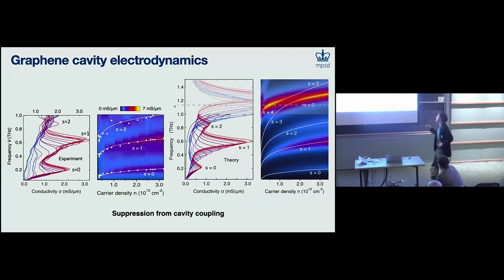So I think there's a few reasons. Clearly, this mode down here, look in the simulation because it's easier. The black line here is the graphene cavity mode. So you can see this mode down here, there's no spectral overlap. There's no spectral weight in the cavity mode, so that's why that mode is not really affected. But as soon as you start to have some spectral weight in the cavity mode, that's when you start to see the suppression happening.